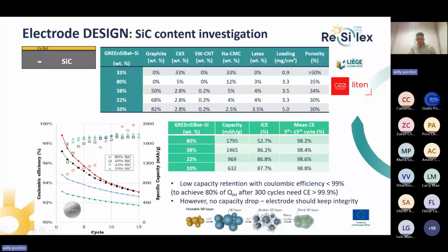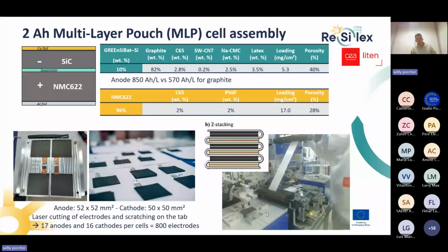Anyway, we assembled some cells, using the anode formulation with only 10% of silicon carbon composite. With this formulation, we achieve 850 ampere hours per liter, which is an improvement of 20% or 50% compared to graphite. And we really reduce the anode thickness with this formulation.